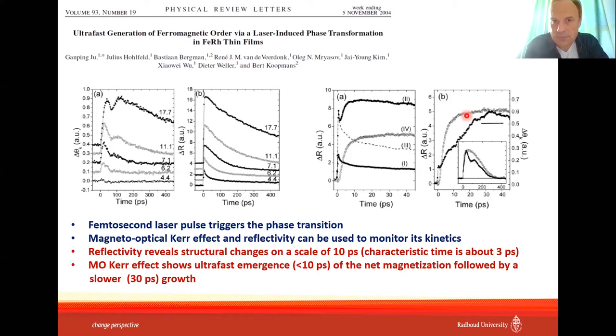Okay, but why don't you have oscillations or something due to this? Yes, I mean, there must be oscillations, of course. You should be able to observe oscillations if these oscillations are not damped. In X-ray diffraction, people saw an onset of oscillations, but I hadn't seen oscillations in optical measurements, which is still possible because the oscillations can be heavily damped here in the vicinity of phase transition.